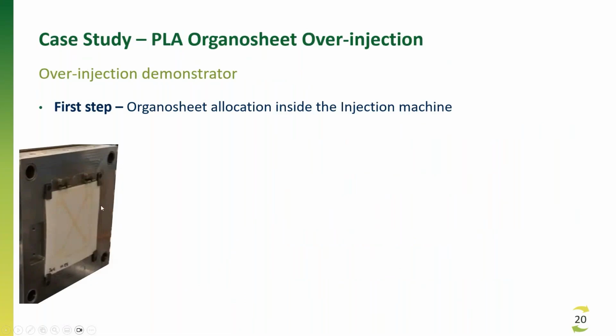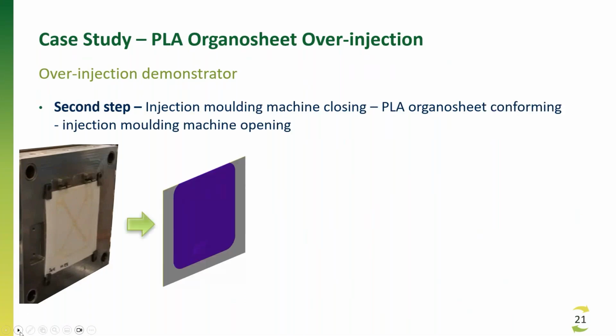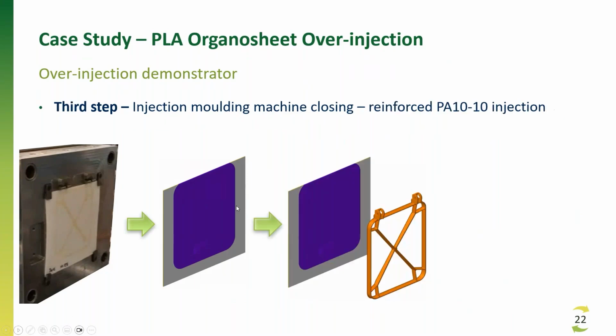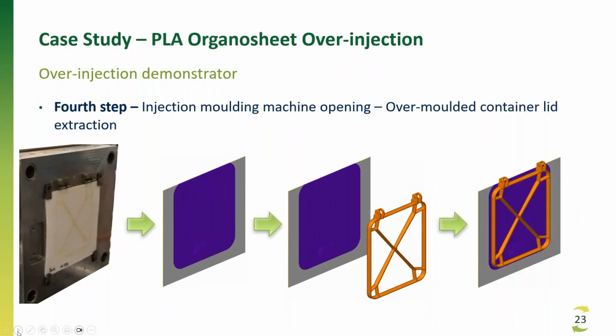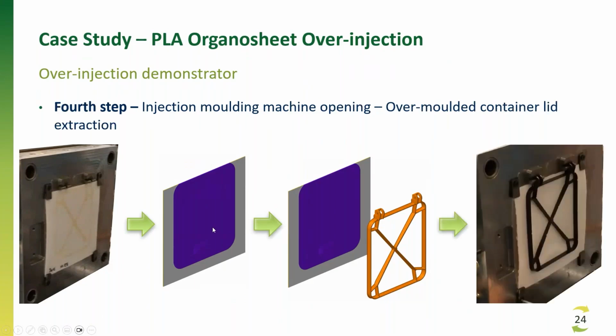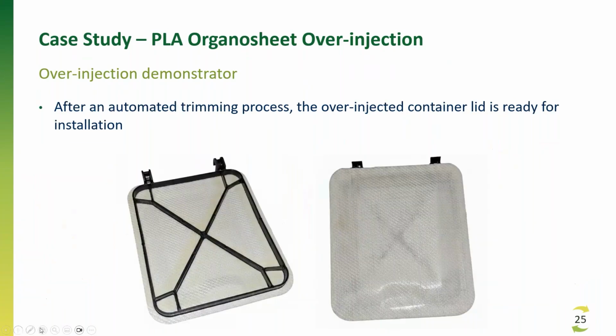lamination. So we took the laminate, placed it into the mold, anchored it, and properly positioned it so that it will fit with the other side of the injection molding. And we over inject it. We have the different steps here. The laminate is thermoformed to introduce the shape. Once we have done the injection, we have to match perfectly the polyamide that we are over injecting with the lines that we just drew on the laminate. Finally, we obtain these materials.